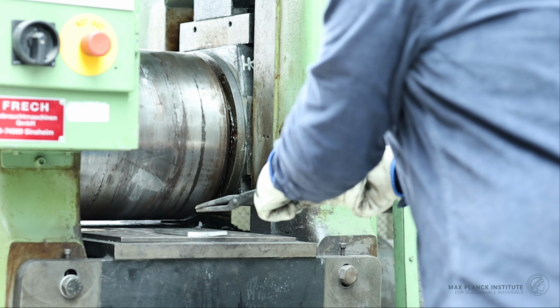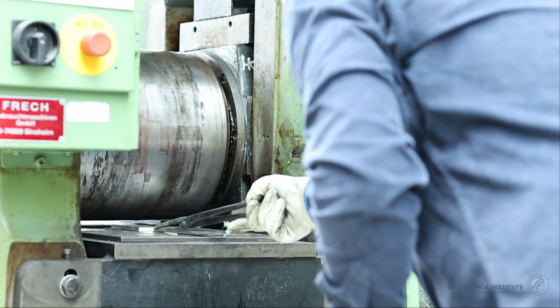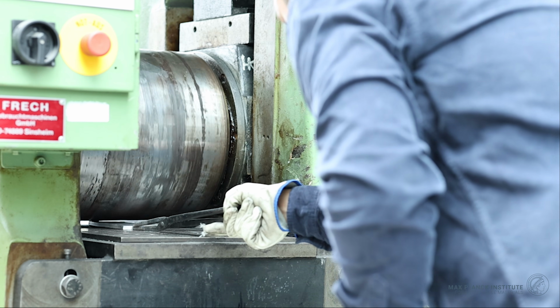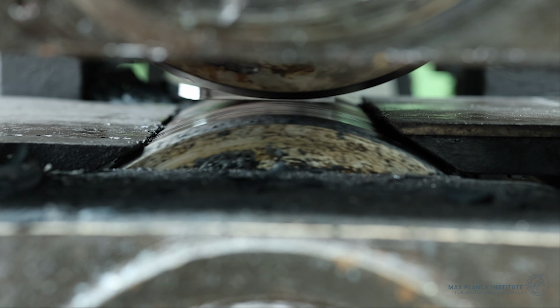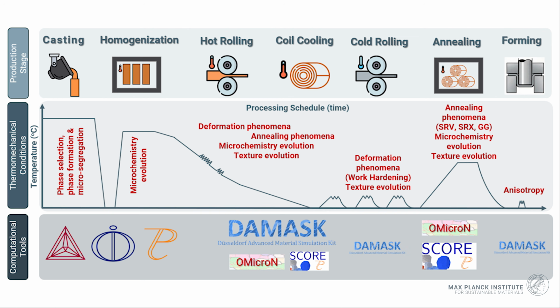What we are doing in my PhD is trying to simulate exactly that. So we are tackling this issue both experimentally, but most importantly, computationally. What we are striving to do is to build a through-process framework that understands the underlying process-structure-property linkages. We are interested in how compositional variability affects the microstructure of recycled aluminum alloys during processing. Therefore, more specifically, we are interested in what we call texture, which then affects those properties.